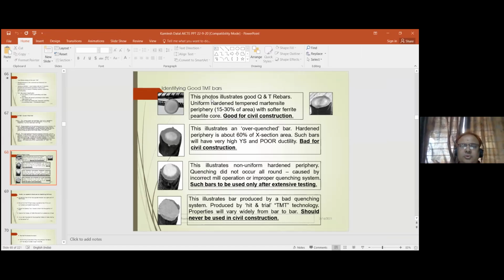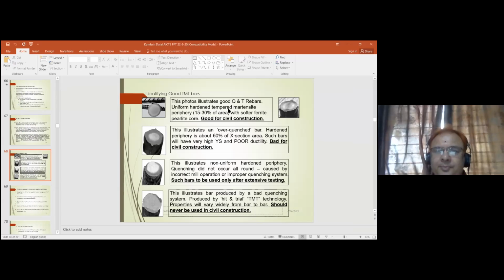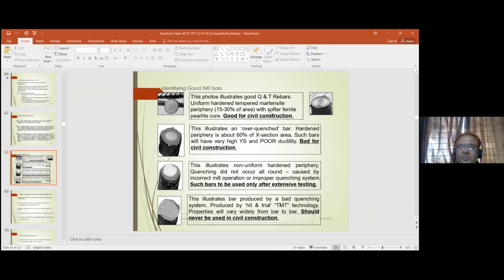Okay. So what is the actual process? So many engineers don't know what the actual process of TMT bar is. This is the cross section of the bar. As per our video, you can see the uniform hardened tempered martensite periphery. This is the martensite periphery. It should be 15 to 30% of the area, and the other in between is the softer ferrite pearlite core, which is good for civil construction.